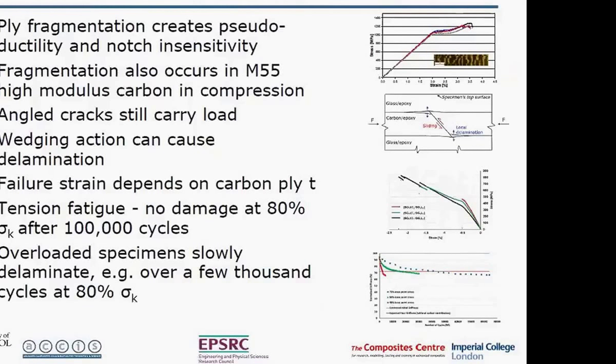But if we look at the M55, which is a high modulus fiber with a relatively low strain of failure, we see the same sort of fragmentation that we see in tension. We get these angle cracks, and those angle cracks enable it still to carry load, and the wedging action can cause delamination. So the failure strain in compression depends very much on that carbon fiber. We use the same sort of approach, damage model maps, to understand that and to predict the response and to design our materials to have the right sort of combination of properties.